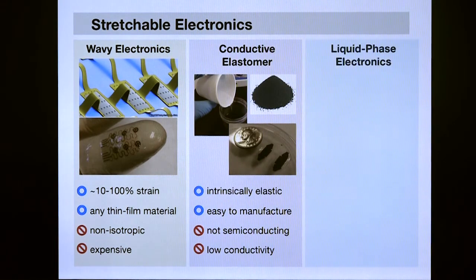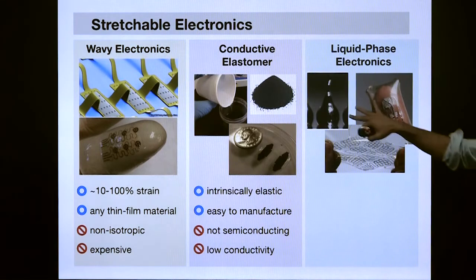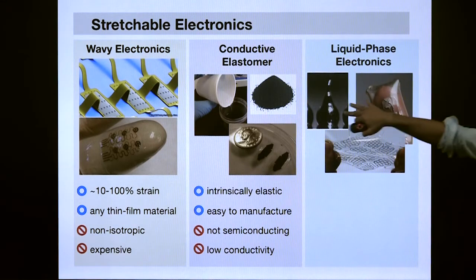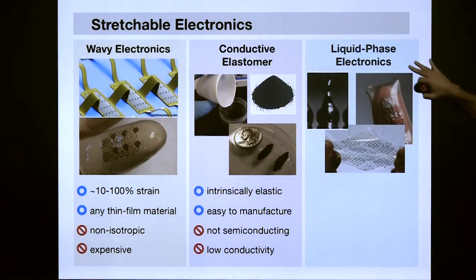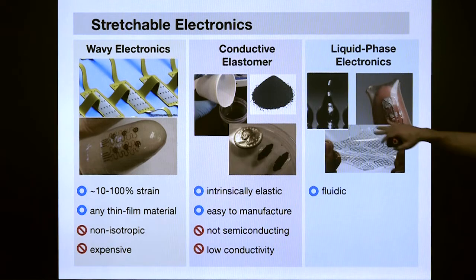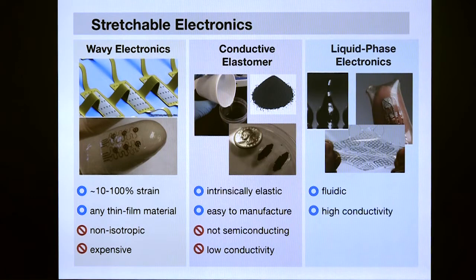So for us, one material that we found to be very versatile, and a very good compromise between these approaches, is to use metals that are liquid at room temperature. I call these liquid phase electronics. Basically, we're taking liquid metal alloys, putting them in microfluidic channels, and sealing them into rubber. So they're just as conductive as conventional metal wiring, but they're in a fluidic state, right? So they can stretch with the surrounding elastomer matrix.